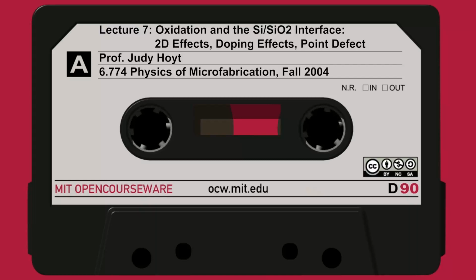After preparing this surface, he then put it in the furnace and grew this thermal oxide on all those free surfaces, which is shown here in blue. That's the silicon dioxide. So that was a real experiment. And then, just like we saw in the previous photo from Marcus and Sheng, he deposited polycrystalline silicon, and that's simply used for contrast during the SEM analysis and to protect the oxide. So he has got this polysilicon over everything.